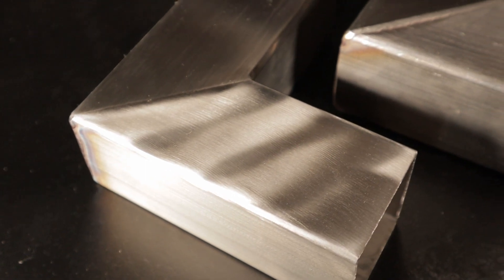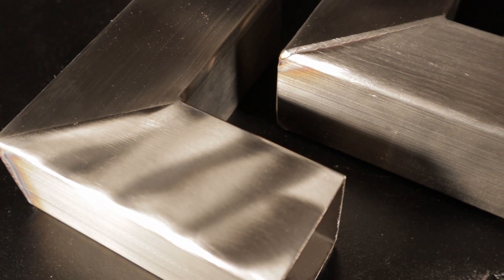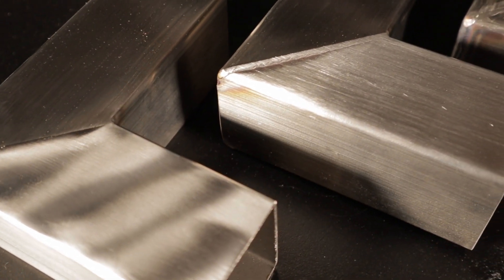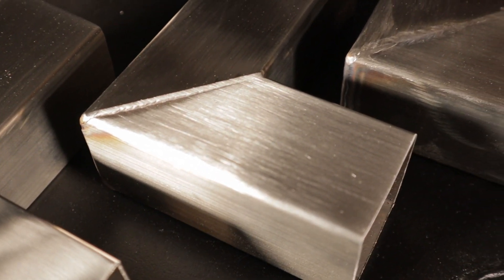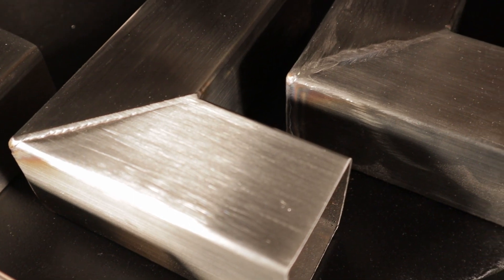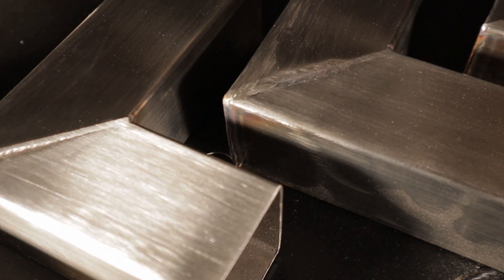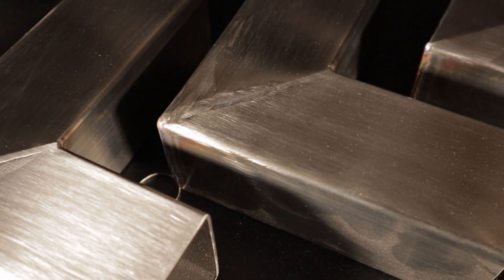I grind the welds back quickly to show the faults. The first is the low amperage. Lack of fusion is evident already. It would crack if it was left like this. Second is the badly misaligned faces. It is sunken too far to polish out. That's a complete redo.